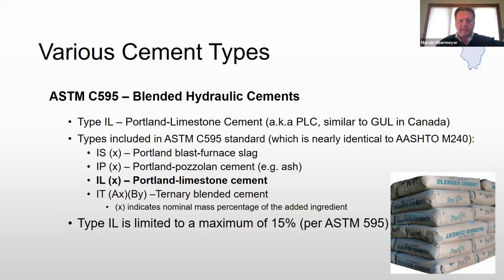You'll notice that IL didn't meet C150. It meets C595 because it's a blended cement. The types of C595 blended cements are Portland blast furnace slag, which is a IS, and that's a type 1 or type 2 cement blended with a blast furnace slag. And that parentheses for the X, that's usually the percentage of blast furnace slag that's added. Usually that's interground. IP many times is interground. Portland pozzolan cement, and that is a type 1 or 2 cement blended with a fly ash usually.